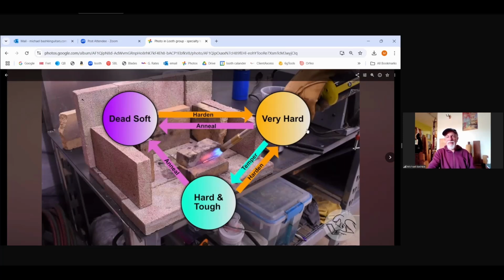What's happening in this state, at least with the O1 steel, and I'm really just parroting some of my bit of research on this, I'm not an expert at all, but as you heat it up, the carbon atoms basically fuse into the iron matrix. A different mineral of iron is produced that I forgot the name of. And you want to try and keep it in this state, which is why you quench it and lower the temperature very quickly. Because as the temperature starts dropping, those carbon atoms start moving, and you start losing your Rockwell hardness.